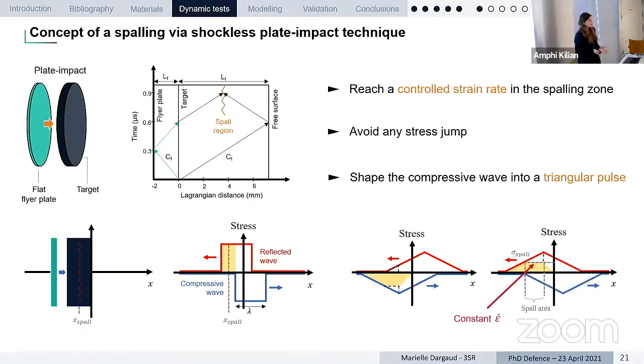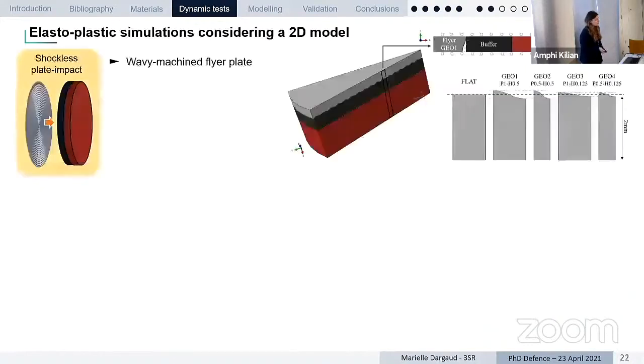So now, how do we get this triangular pulse? To do this, we did some numerical simulations where we decided to pattern the front face of the flyer plate. We patterned it with some wavy shapes. These wavy shapes aim at changing the shape of this compressive wave. So here you have numerical simulations where, in the end, we used a 2D model to be able to design the front face of the flyer plate.